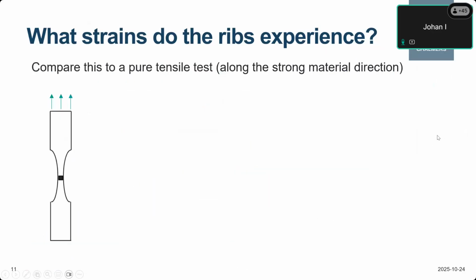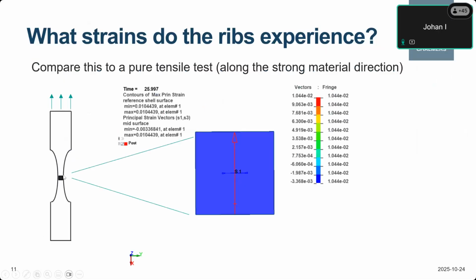If we compare that to a uniaxial tensile test, which is what we have to create the risk functions, that would look something like this. You extract a coupon along the length of the rib. If we zoom in on the material in this part of the material test, we can see a strain state that is very similar to what we saw in the rib. We have the maximum principal strain pulling in tension here, and in compression, and then we have some compression here in the other direction.